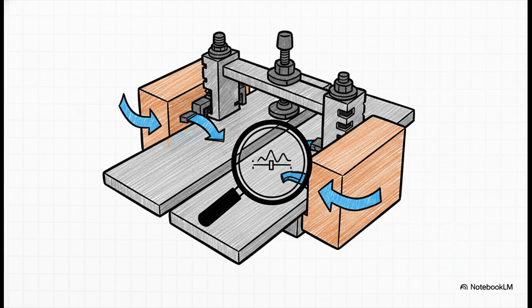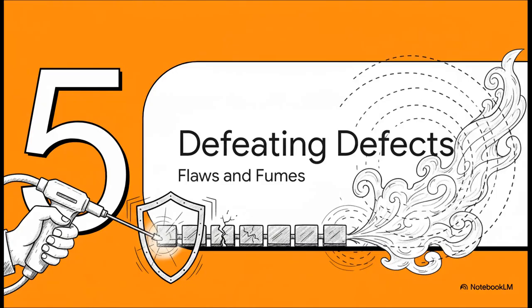So, let's bring it all together. No filler wire means zero room for error. And that leads us to one of the fundamental truths of this process. The fixture is the welder. Your tooling, the clamps holding the part, has to be surgically precise. It needs to hold that gap to less than 1/10 of a millimeter, while huge copper blocks, called chill blocks, are right there, sucking the heat out of the part as fast as possible to keep it from turning into a pretzel. Okay, so you've got your laser dialed in, your gas is perfect, your fixture is a masterpiece, you're ready to make a perfect weld.